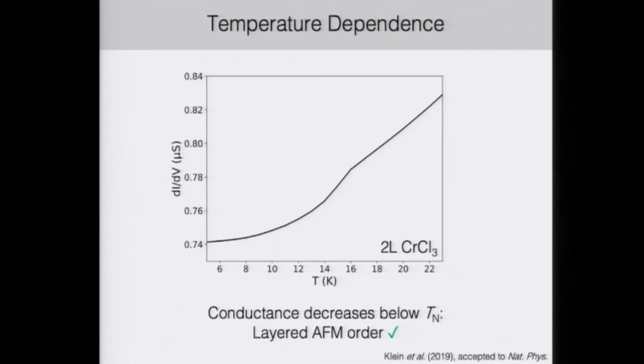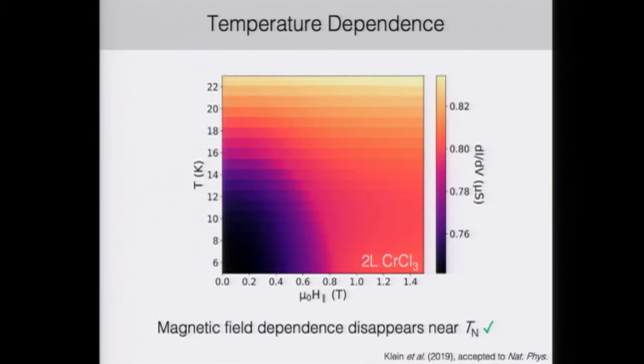So first, we can look at the temperature dependence as we cool down one of these devices as a check. And so we see that the dI/dV decreases below the Néel temperature with a little kink here, indicating the onset of antiferromagnetic order. So far, it looks like a layered antiferromagnet, just like the bulk. We can also take a look at the temperature dependence of the magnetoresistance in these junctions, and we see that the magnetoresistance vanishes roughly above the Néel temperature of chrome chloride. So far, it looks just like bulk chrome chloride. It looks like a stack of layers.